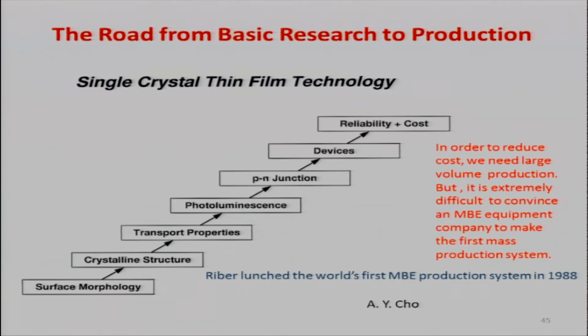And of course, next level higher is look at the photoluminescence. Now you look at the minority carrier device. It's harder yet. And then you can make PN junctions. Hard, PN junctions is not easy. You have to have interface very smooth and doping profile abrupt changes to get good PN junctions. After you did all that, I can start make devices. So you make a device, you can publish a paper. But then, the important thing is, you can't just make a device which lasts 10 minutes, get the data and publish a paper. You gotta make a device which will last 10 years and 20 years to be any useful.